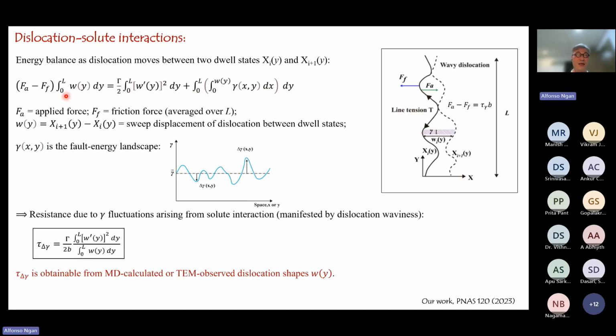The term on the left-hand side is basically the work done by the applied force minus the lattice friction. And then on the right-hand side, we have two terms. This first term is due to the fact that the dislocation is no longer straight, so it is longer than a straight dislocation, and therefore you have the line tension, this gamma, that I introduced in my slide number 1. So this is the line tension energy, if you like, for a wavy dislocation as compared to a straight dislocation. And this second term would be the work dissipated as the dislocation sweeps through this stacking fault area. So this is the energy balance.